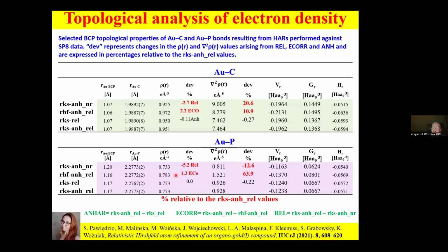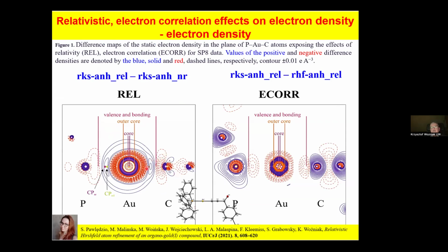We can get information how big are those effects. But the most interesting are changes in distribution of electrons. So these are differences in two electron density distributions showing relativistic effects. This means that relativistic effects at the gold atom are associated with shift of electron density to outer regions, and we have increase of electron density in the valence part of electron density distribution.